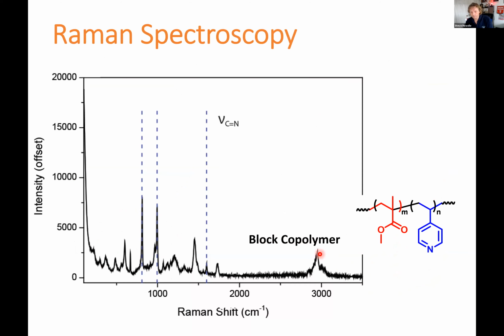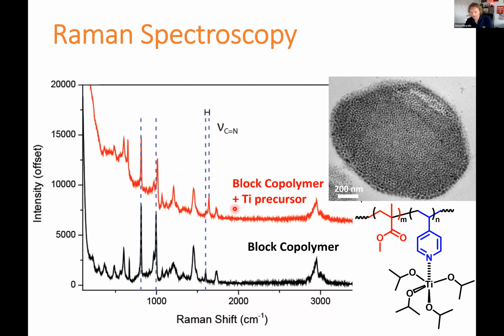So here you can see that we proved using Raman spectroscopy. The bands of the CN are clear. After we put in the titanium isopropoxide precursor, you can see a shift in the CN bands, which shows us that the titanium goes into the zone where we want it to be.